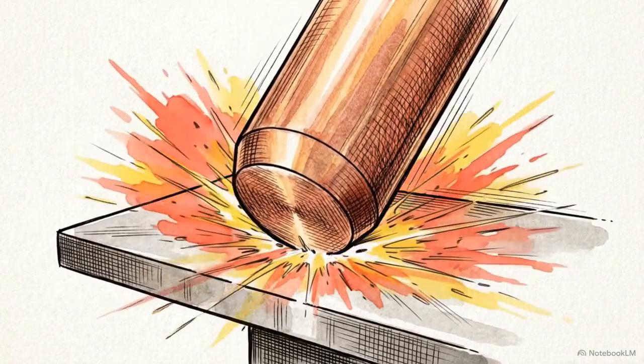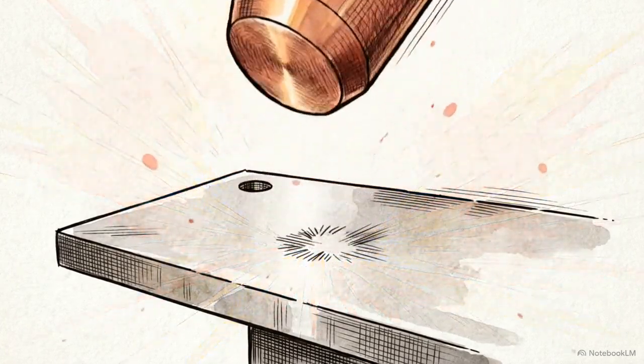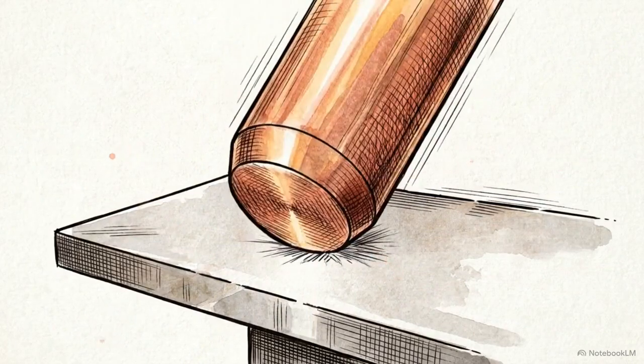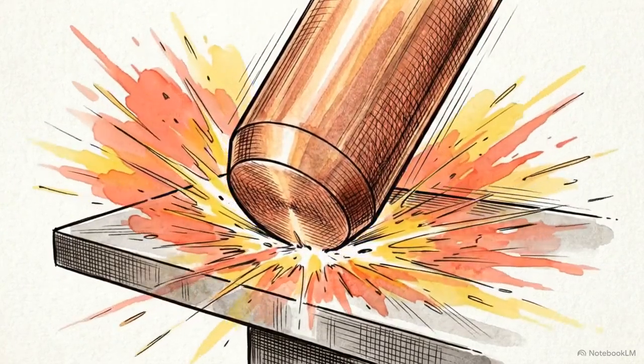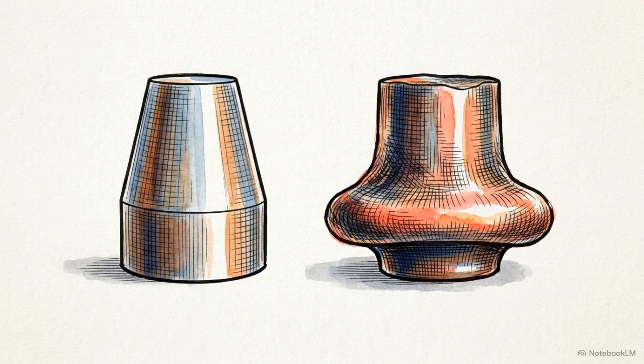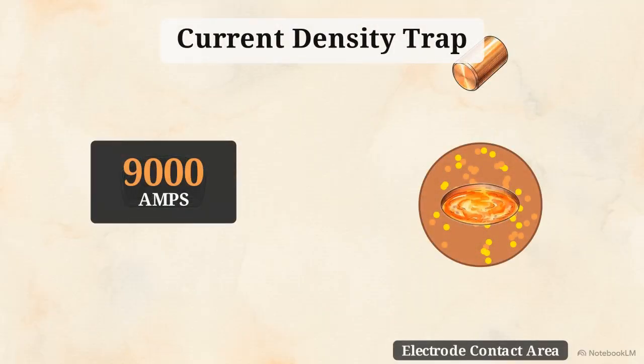That assumption ignores physical realities. The tooling takes a beating. Copper electrodes absorb thermal shocks and mechanical impacts thousands of times a shift. Over time, this repeated cycling causes a defect known as mushrooming. The copper alloy tip gradually softens, flattens out, and widens. This expansion creates a current density trap.